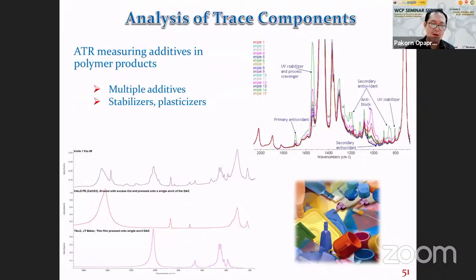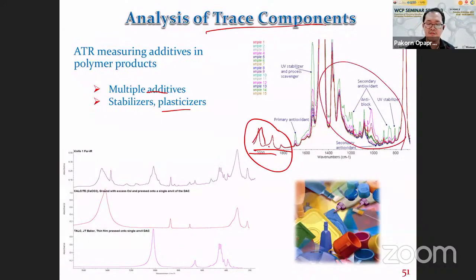We can use this to identify trace component in materials. For example, if you have additive or plasticizer in very small amount in your sample, you can use infrared spectroscopy to identify them. But you need to normalize peak that does not have different characteristic, to make them have the same intensity, and find different feature in other region. Try to identify information.